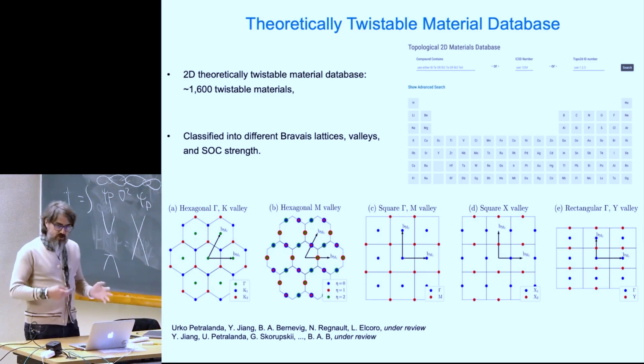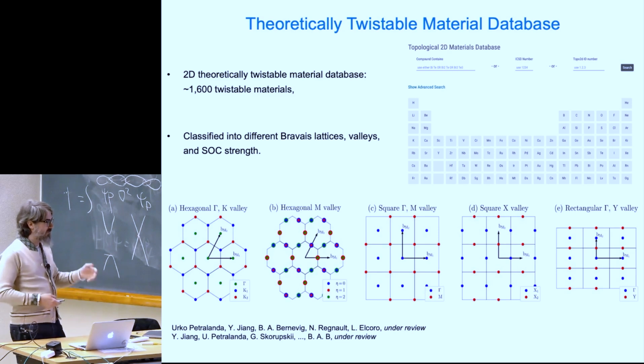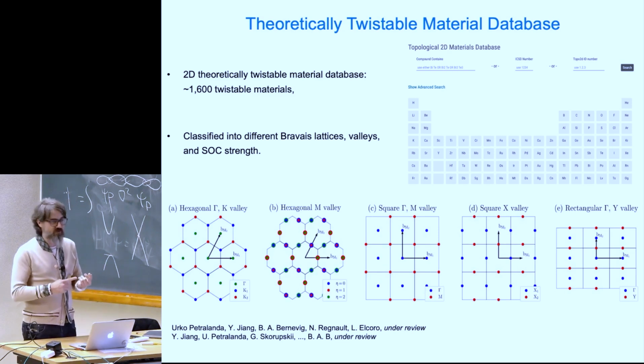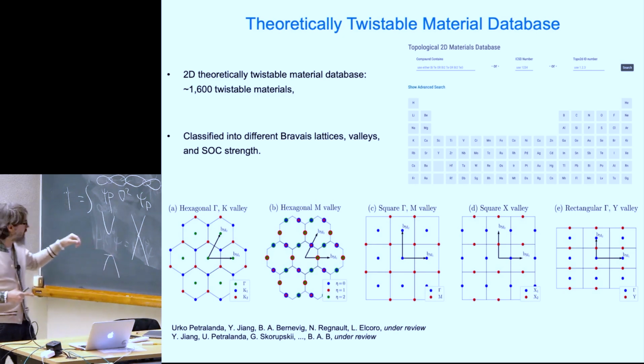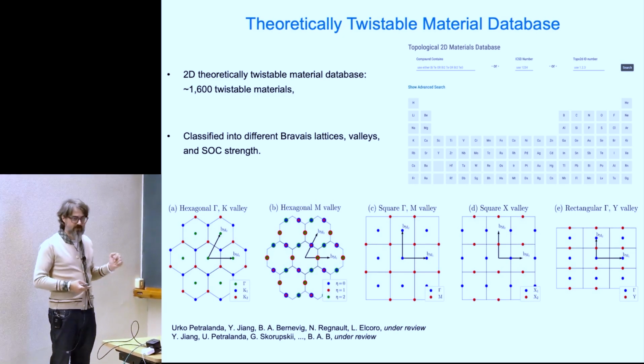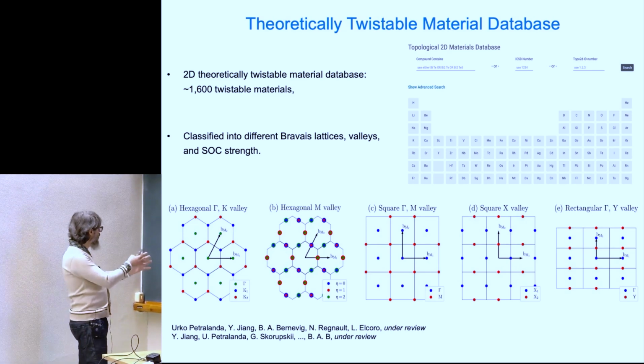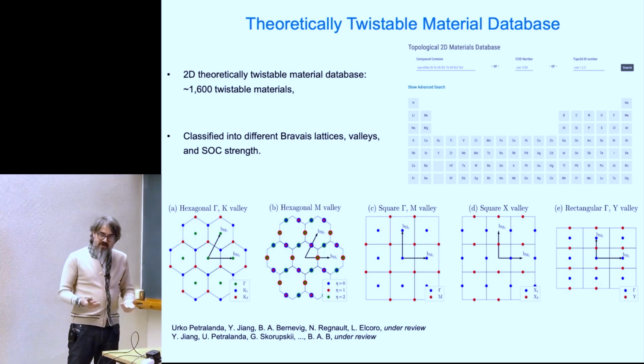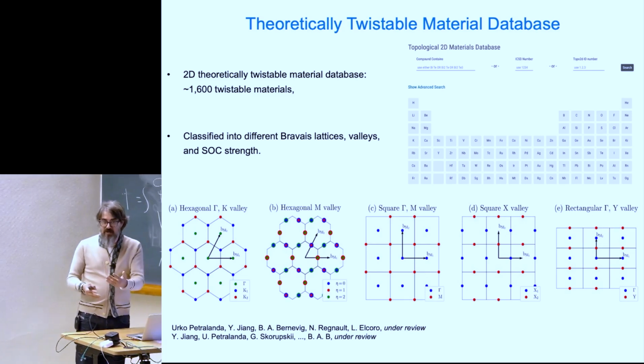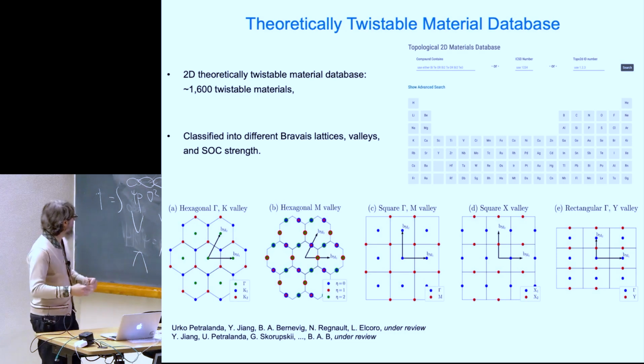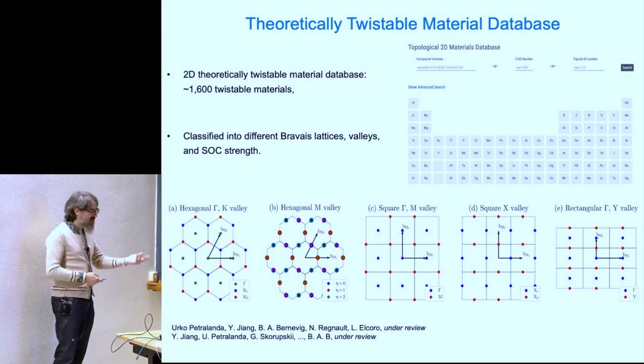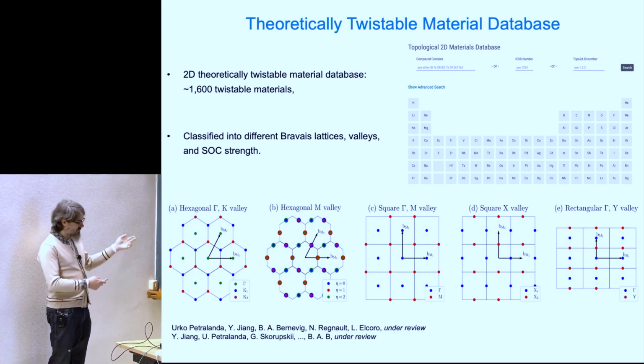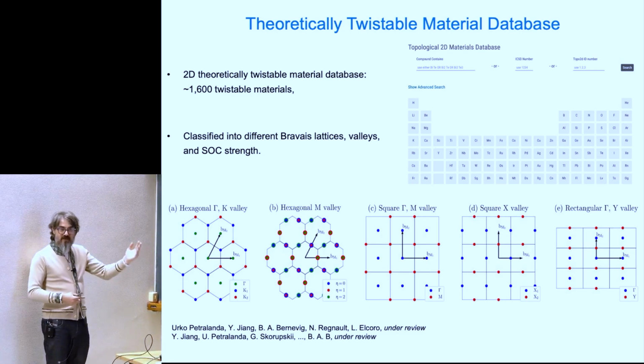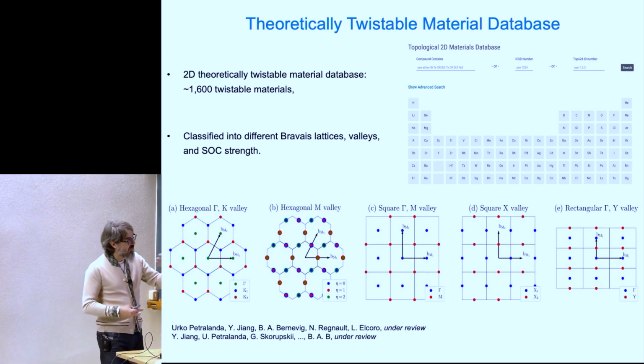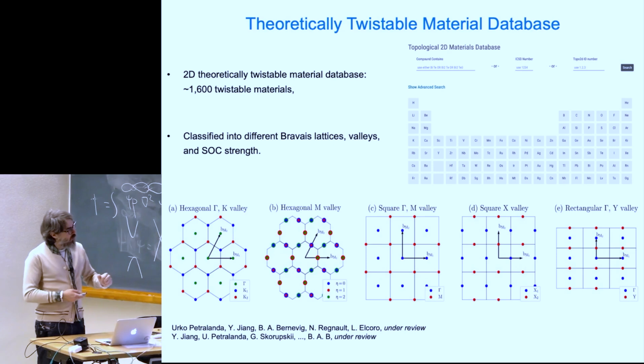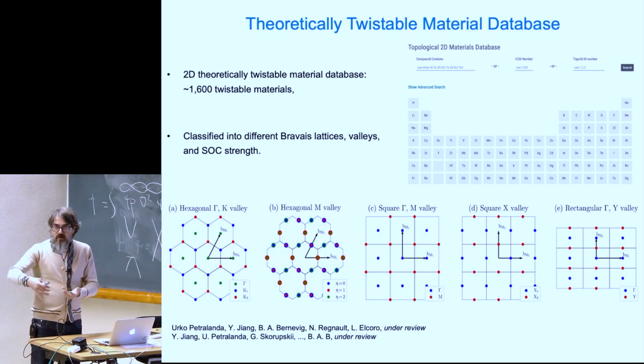But if you want to put some order into what you twist, you basically have to realize that, number one, the only thing you can twist and have theoretical predictions are clean band structures. And that's why people have twisted tungsten ditelluride. Okay, someone has twisted tungsten ditelluride. The theory there is useless because the band structure that you start off with in the monolayer is too complicated. So then when you twist, it's just going to be even more complicated. So that's why, I mean, the results are nice, but for the theory, there's no way to predict things. Now, for things that look simple in the monolayer, you might have some hope of predicting the band structure in the twisted samples. And then you can put some order. You can ask, where do I want my monolayer band edge to be?